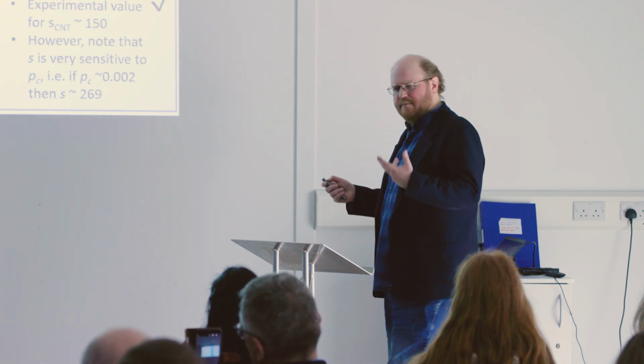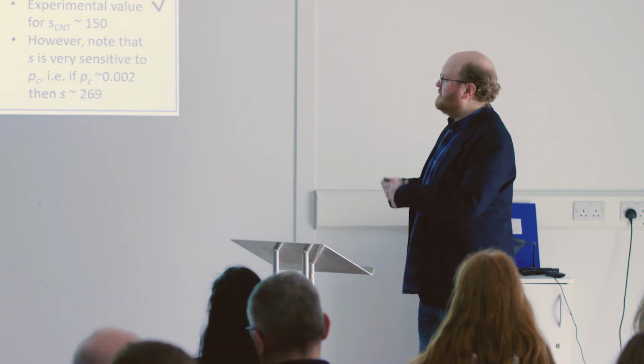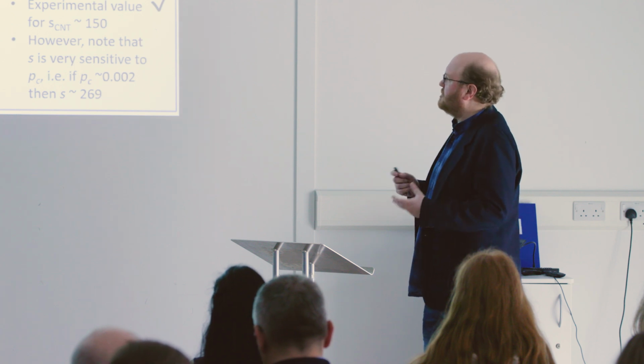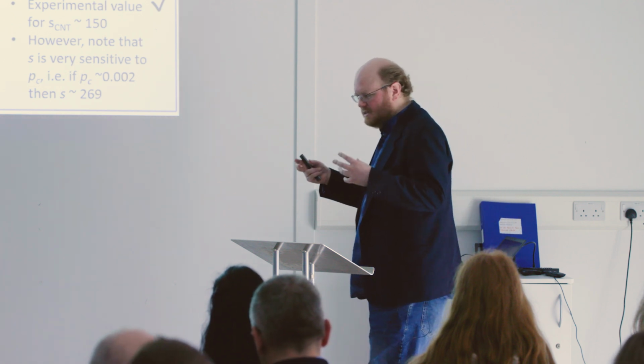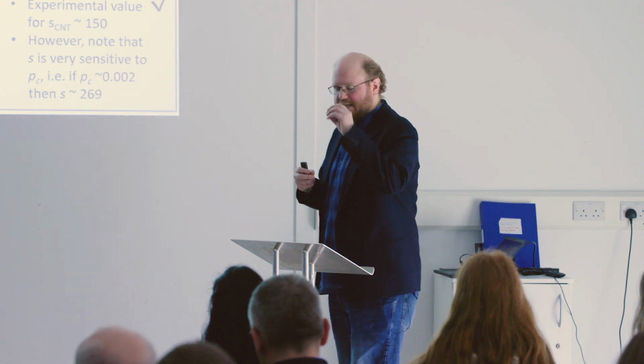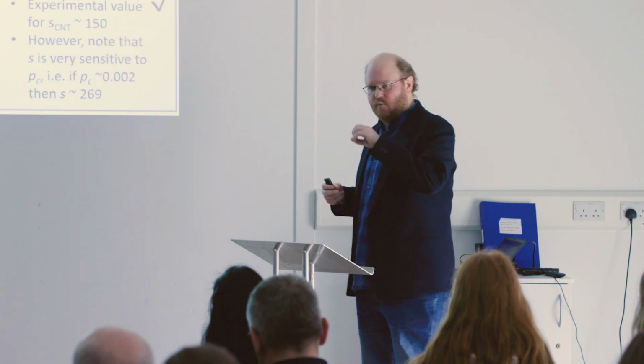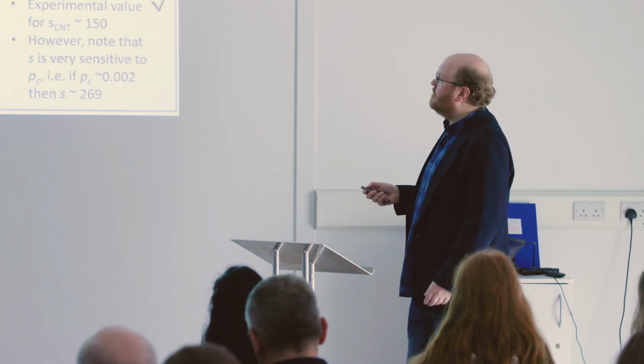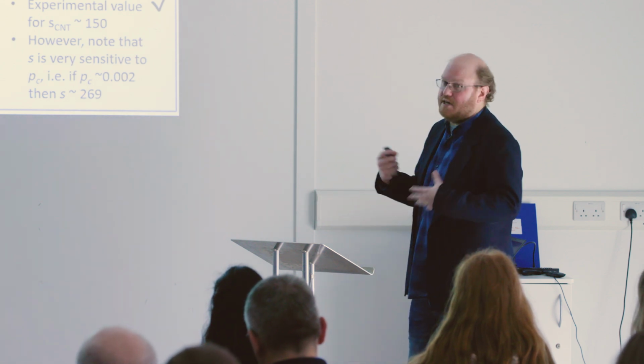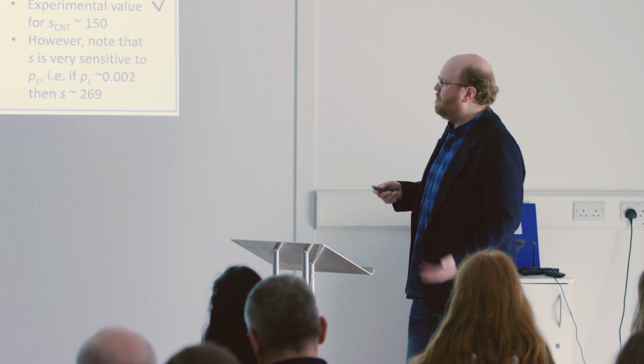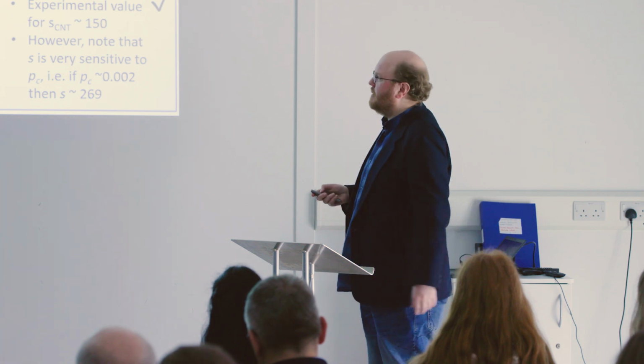The carbon black behaved a bit differently than we expected. There's obviously some clustering, but because of the way it clusters, or the way it interacts with itself, its individual particle aspect ratio isn't what's important, it's the cluster aspect ratio. So for that one, we have to adjust our model to take that into account. That's a bit beyond what I want to talk about today.